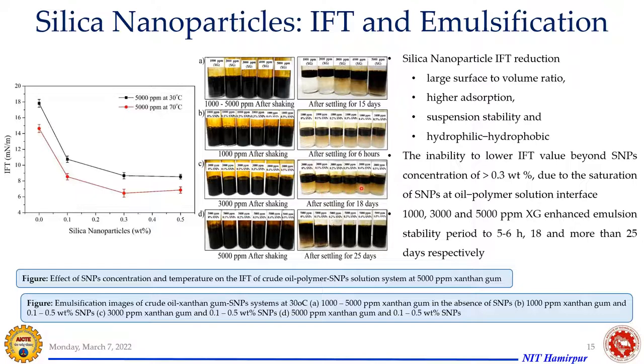So you can see here, it is having your emulsification behavior, because nanoparticles, why it is showing that case? Because nanoparticles have a large surface to volume ratio. So that could accumulate more amount of surfactant or other chemicals on its surface. So it is the interfacial film properties. So the oil water interface is getting more compact with more chemicals. So that's why you can see, because of this large surface to volume ratio, there is higher adsorption of chemicals on the nanoparticle surface. So the suspension and stability of hydrophilic and hydrophobic interactions are also getting improved.